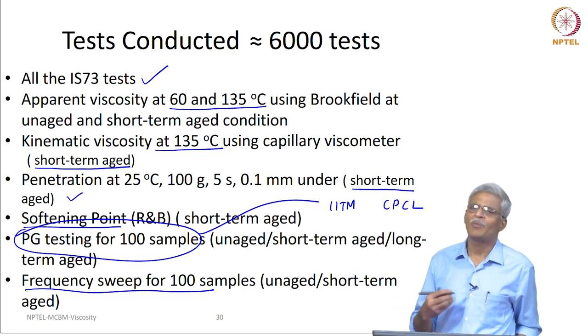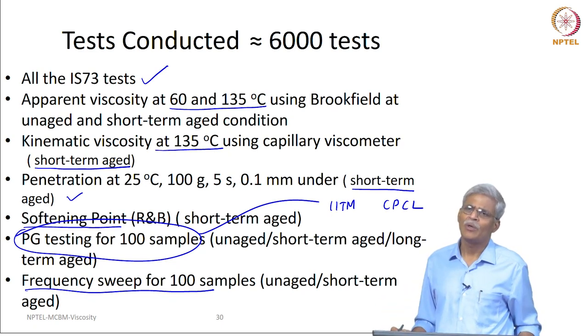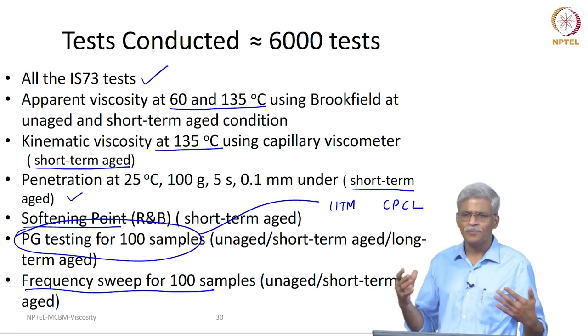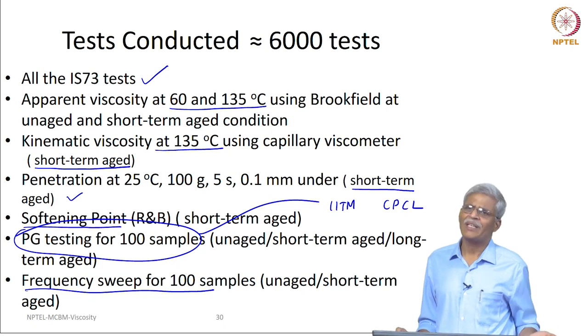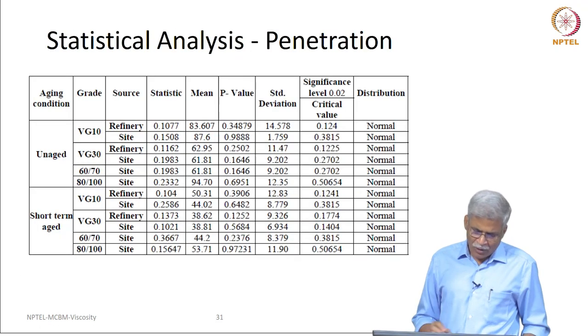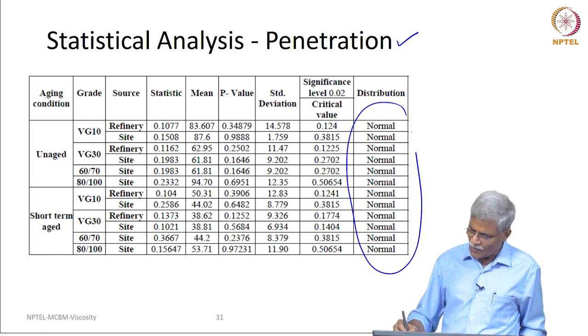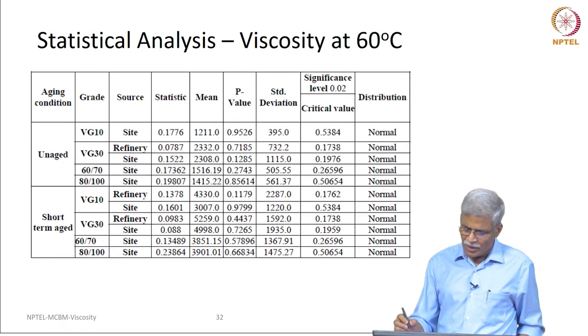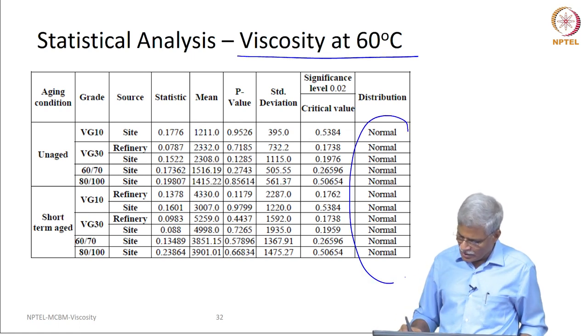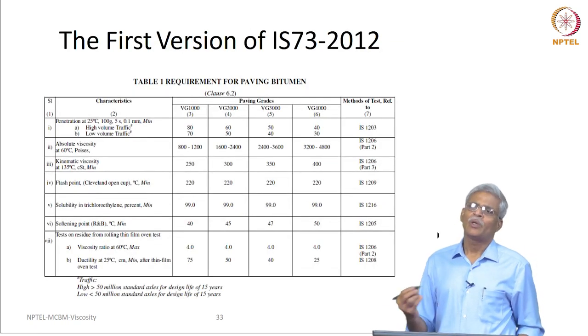By this time you should be familiar with what a frequency sweep experiment is, what a master curve is, and what thermorheologically simple behavior is. If you are able to have two materials whose master curves lie on top of each other, you can safely say that the temperature susceptibility of the materials is more or less identical. We did a lot of statistical analysis — we wanted to check whether the distribution of penetration and viscosity at 60 degree centigrade is normal — and based on all these things and structural simulations, we proceeded.